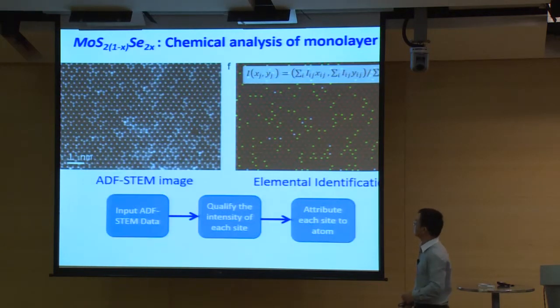Okay, so here we have a STEM image showing like this, and by resolving the intensity mapping, we're able to translate the STEM imaging to the visualized image showing the distribution of each atom, like the white dots are 2 selenium, and the green dot 1 selenium and 1 sulfur, and the red dots are moly atoms, and the very dark green dots are the 2 sulfurs.